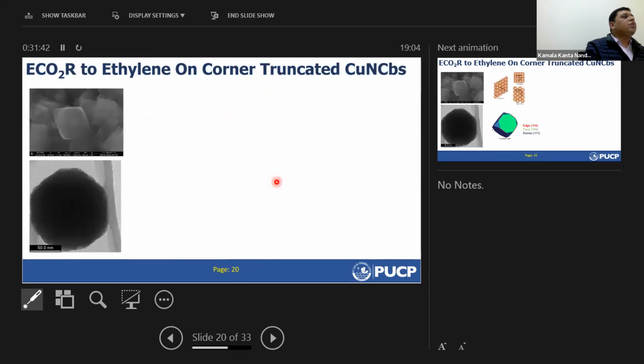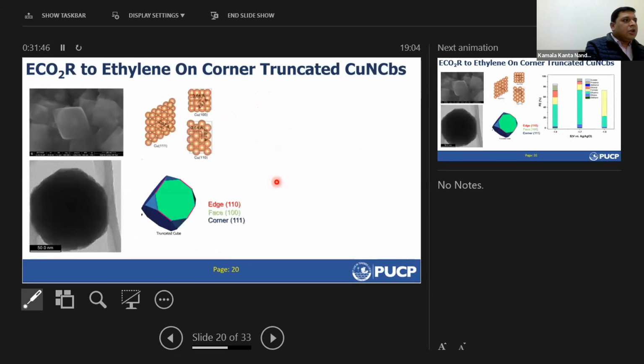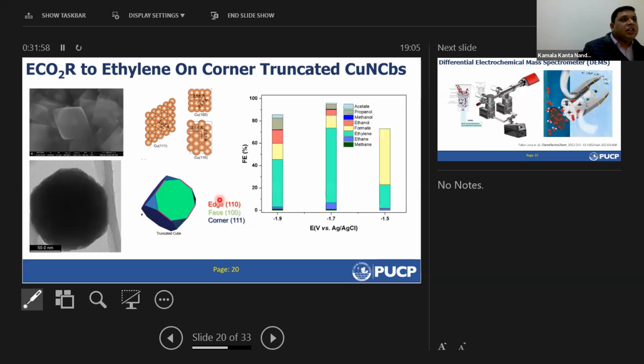Also, we produced a higher amount of ethylene on corner truncated copper nanocubes. And you can see that the copper nanocubes, which are corner truncated, have a higher amount of 100 facet, and there is some fraction of 111 facet, and this is actually assisting in the formation of ethylene, and we got around 60% Faraday efficiency of ethylene in the CO2 electroreduction process.